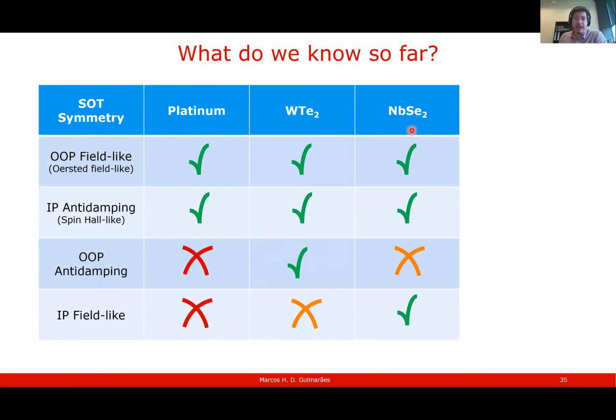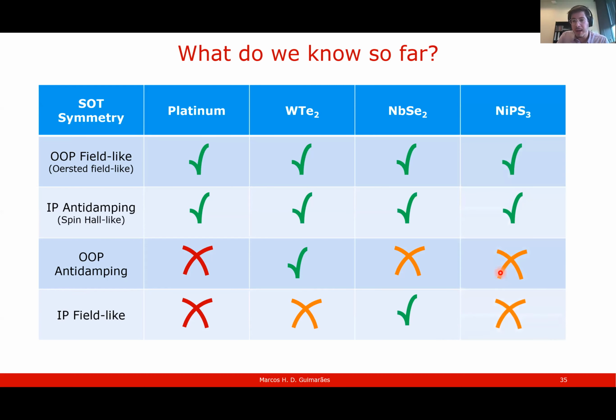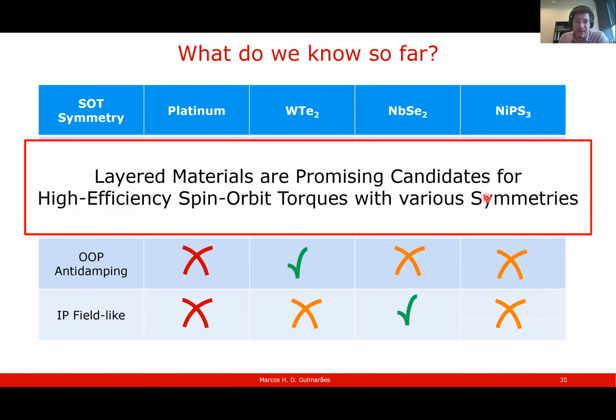The niobium diselenide, I should say strained niobium diselenide, is actually the other way around. We observe the in-plane field-like, but not the anti-damping out-of-plane torque. And the nickel thiophosphate, we observe neither, even though they are allowed below the Néel temperature. But this gives you that.